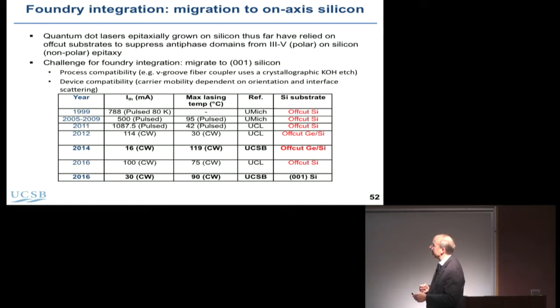So this is the evolution. There's been a lot of great work here out of Connie Chang-Hasnain's group on growing III-Vs on silicon, growing ribbons up and making lasers out of it. These are all in-plane structures. Going back to early work, everybody grows off-cut, right? Because you're growing a polar material on a non-polar substrate, so you've got stacking faults, lots of issues. If you grow it off-cut, there's distinct improvement in the performance.